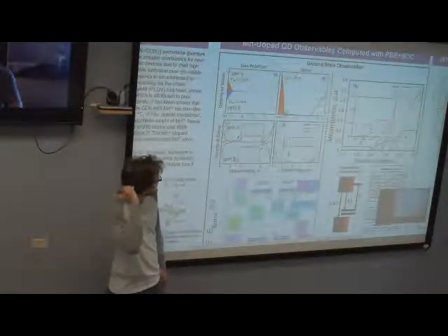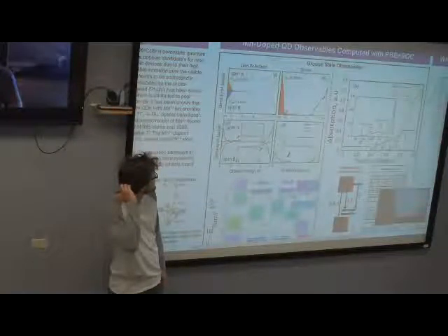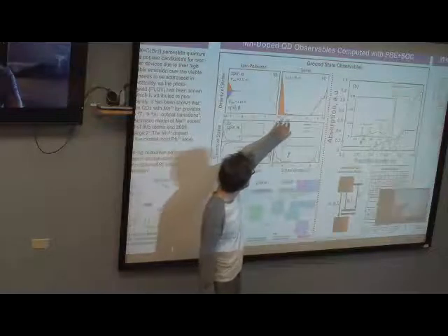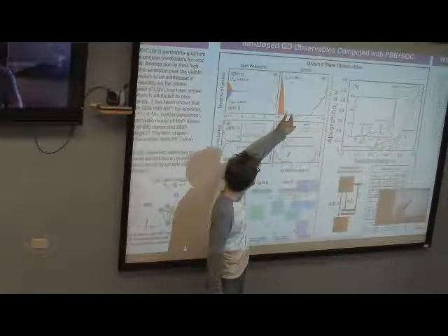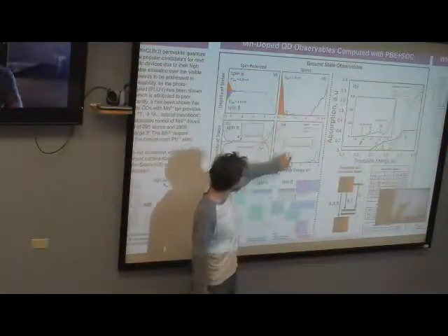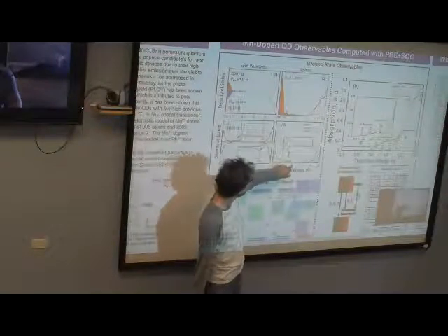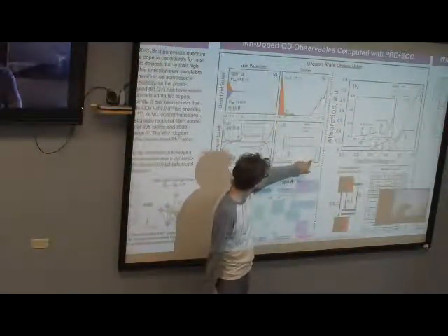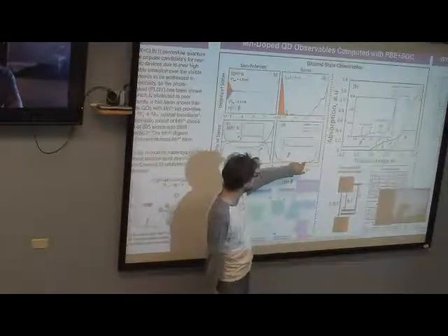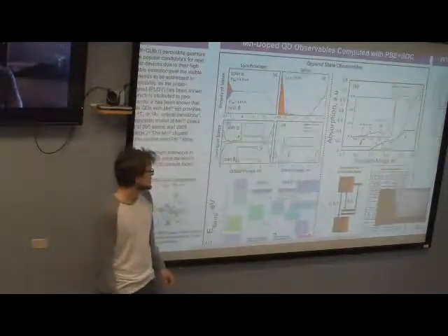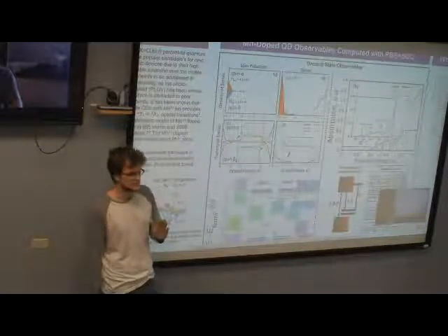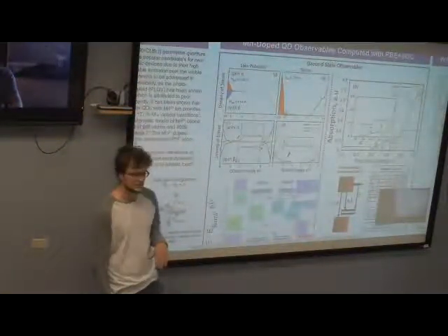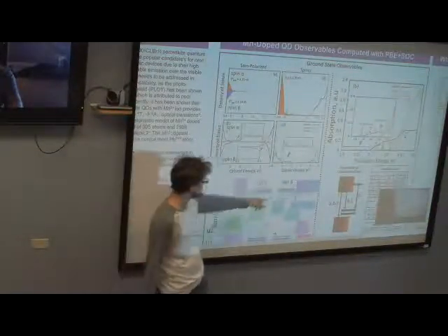But when we do our spinor computed ground state electronic structure, we still see that we have these two D states in the middle of the gap. And then when we look at our PDOS, we see that the Mn2+ states that were originally at the conduction band edge get pushed deeper into the valence band due to a strong spin orbit coupling of the perovskite P orbitals to reduce the band gap.